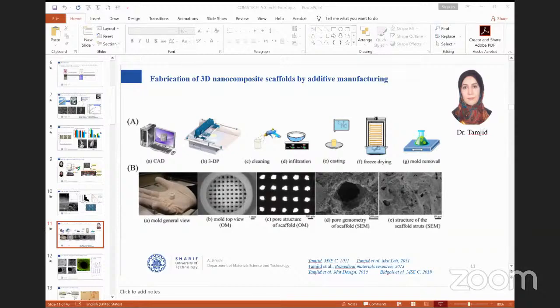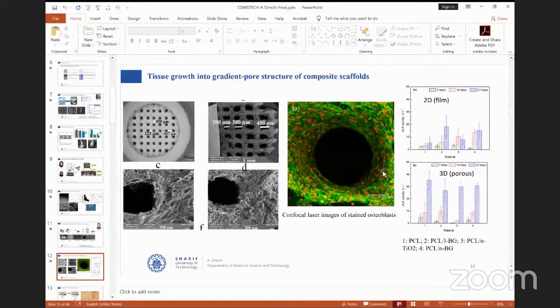As you see here, the sacrificial molds from plaster are made with a special porosity which is needed for a scaffold, and then we fill it with composite materials that could be a polymer incorporated with nanoparticles, bioglass, hydroxyapatite, and so on. Did freeze drying, and then remove the mold to make three-dimensional scaffolds. And this gives us an opportunity to design the porous structure of the system. Especially, we have found, I'm going to slide 11 now,